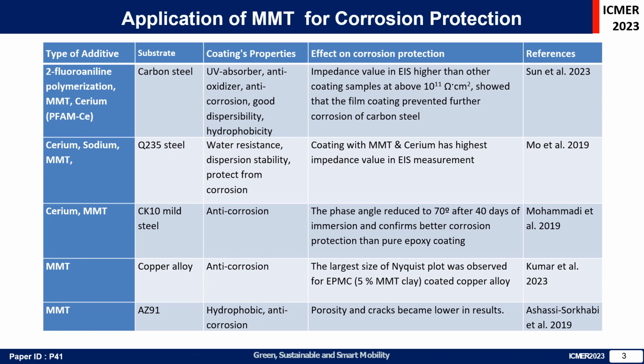Mohammadi et al. used cerium and MMT on CK10 mild steel. Their coating shows anti-corrosion properties. Their results show the phase angle reduced to 70 degrees after 40 days of immersion and can confirm better corrosion protection than pure epoxy coating.